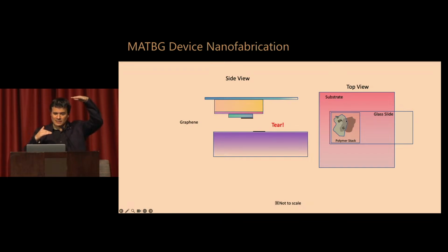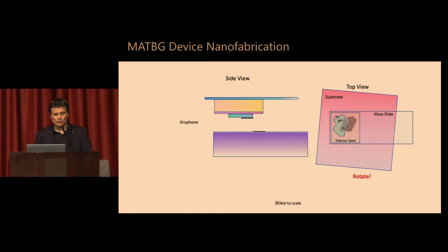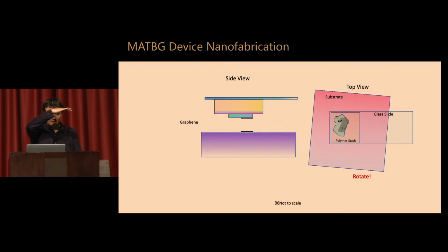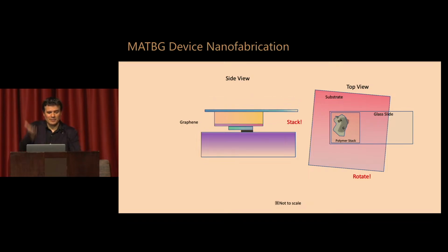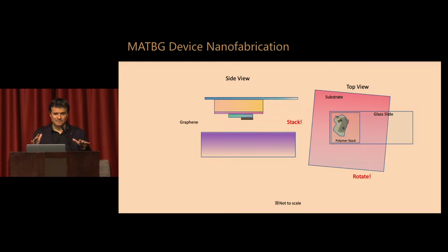But even though these are at different heights, the two pieces of graphene come from the same crystal. So the atomic rows here are aligned with the atomic rows here. I know exactly what the orientation of this is with respect to this. So what I can do now is rotate my substrate by any angle that I want, for example, 1.1 degrees, why not? And then I can translate this polymer with the top graphene layer, and stack it on top. And I pick up the second layer of graphene.